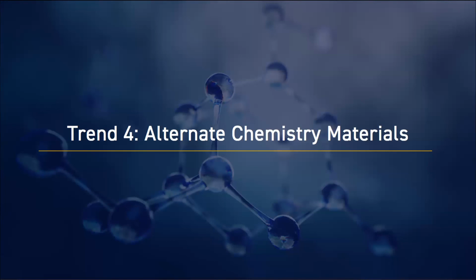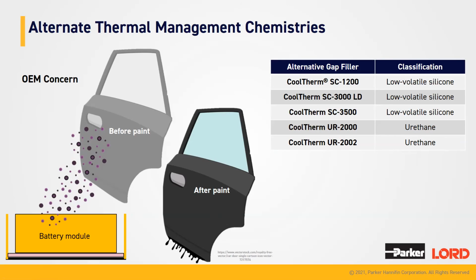And finally, let's look at trend 4, alternate chemistry materials. So looking at alternate thermal management chemistries, one of the concerns that OEMs have specifically with silicones is that the off-gassing or the volatile siloxanes will affect some uncoated surface, like a door, for example. And once that door goes through the paint process, you can see that the paint won't stick and it will actually drip off the door. So OEMs are constantly pushing for ways to mitigate these volatile siloxanes.